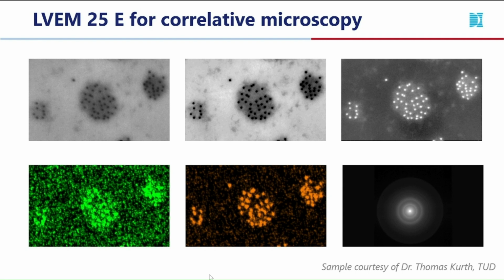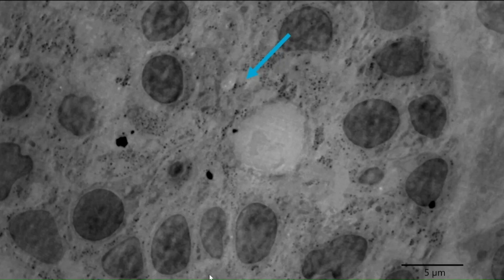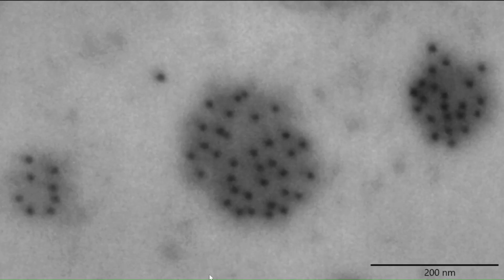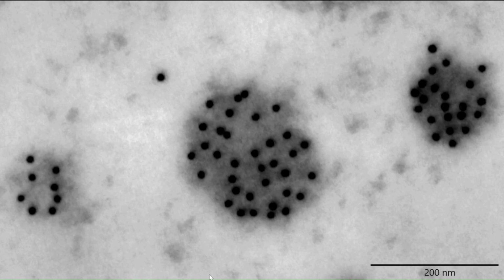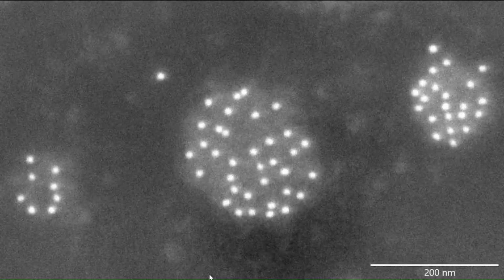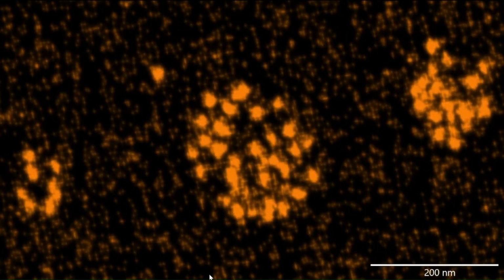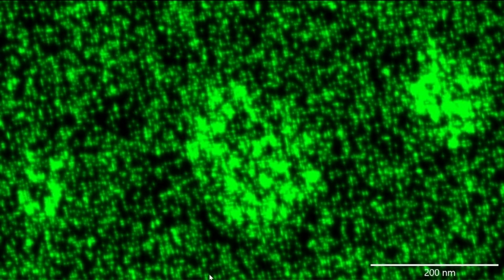LVEM25E can provide such correlation during one imaging session, as in this case of zebrafish pancreatic cells with golden immunolabeling concentrated in insulin. So, during one imaging session, we can easily get a quick sample overview in TEM and quickly find the point of interest. Improve the contrast and resolution of this thicker sample in STEM. Check the metallic character of nanoparticles in SEM with backscattered electrons. And verify in EDS that the metal is gold and that the gold is bound to insulin, which has a high share of sulfur. And we can also add electron diffraction, all from one sample, one device, and one time slot of about 1 hour.